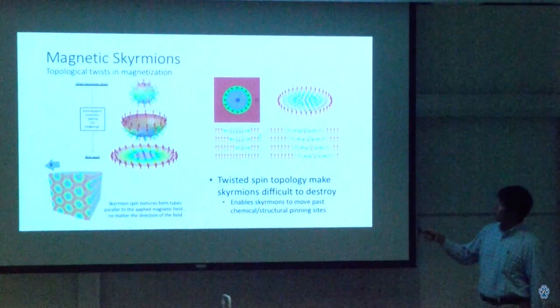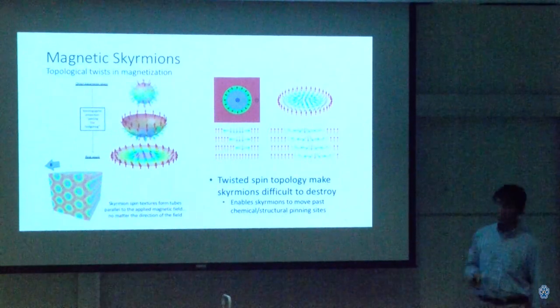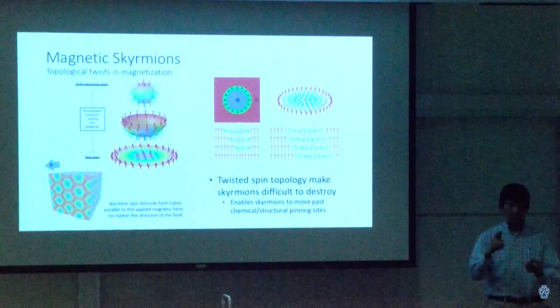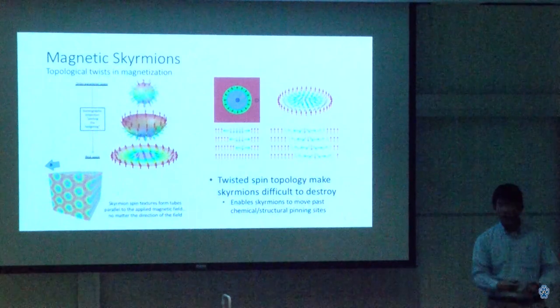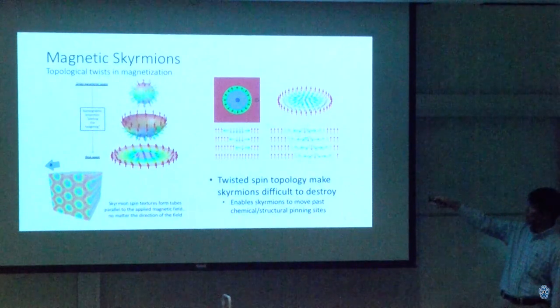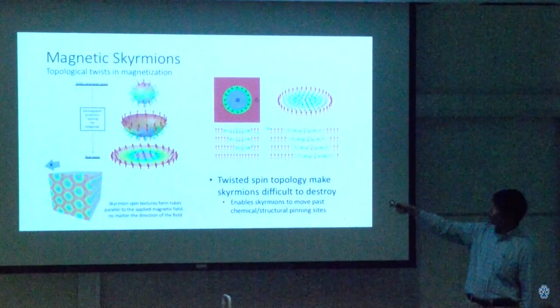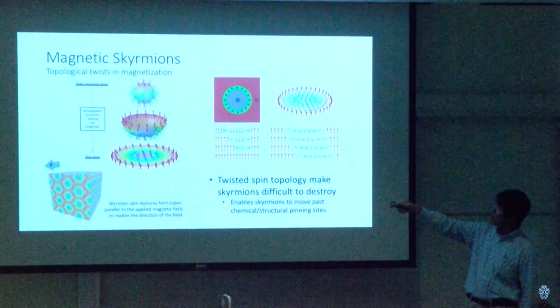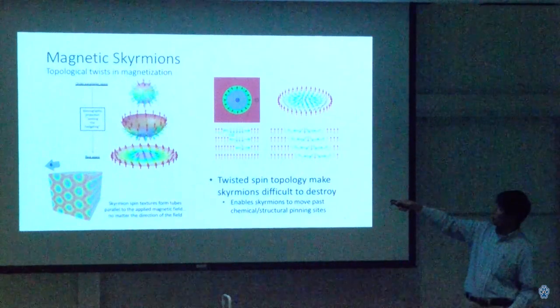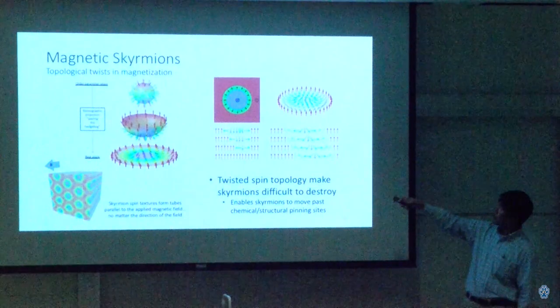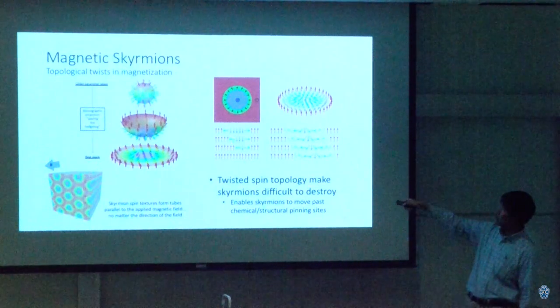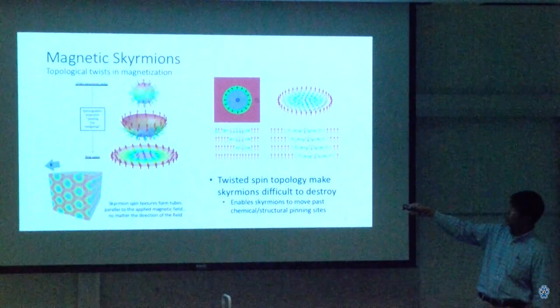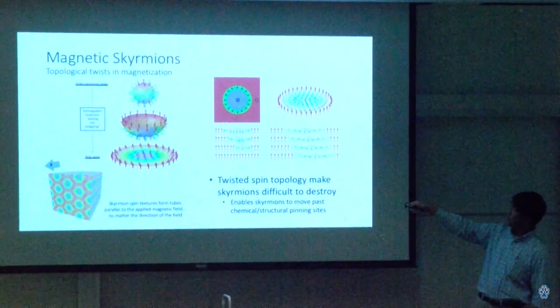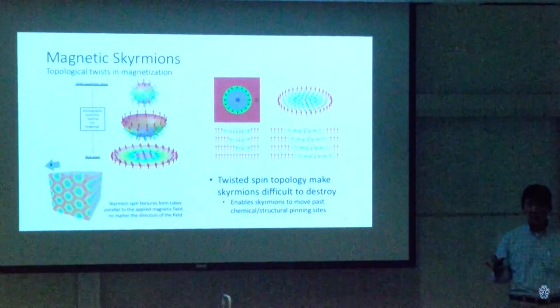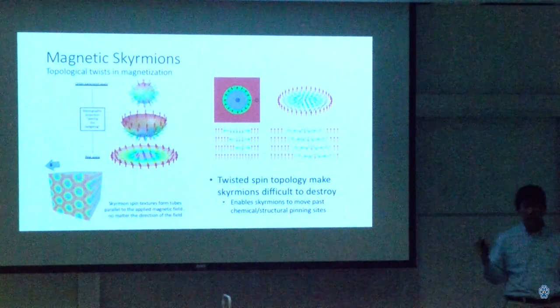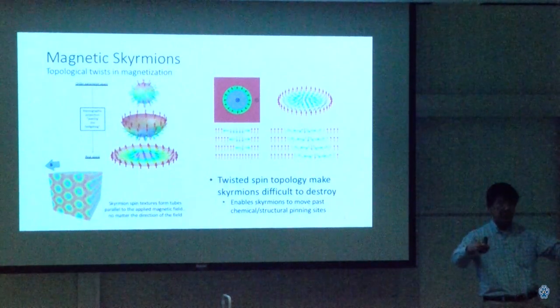A magnetic bubble may superficially look like a skyrmion, but it's missing several essential ingredients. For example, it may have exchange, but not a spin-orbit interaction that requires the spins to have a coherent rotation in one way or another. As a result, if I try to change one spin at a time from, say, down to up or sideways to up, going from the top line down, you can see that I'm flipping the spins from sideways to up, converting a green to a red arrow. And I can just very smoothly eliminate the blue arrows until the magnetic bubble completely shrinks away to zero. That's the equivalent of just twisting a string.